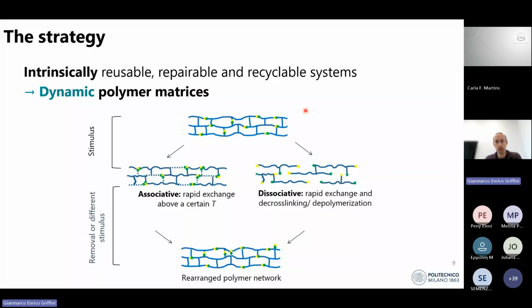On the other hand, we have dissociative networks where we introduce, again, reversible covalent bonds that can lead, in a certain range of temperatures, to the breakage of the bond. Then the material can behave as a sort of thermoplastic system, and upon cooling, the material can recover the three-dimensional structure typical of cross-linked materials. During this heating and cooling, we get to the conditions where the macromolecules can actually flow, and we can get again reprocessing, recycling, and repairing. In both cases, we lead to a polymer network that can actually move in certain process conditions, and ultimately lead to circularity of the polymer network itself.